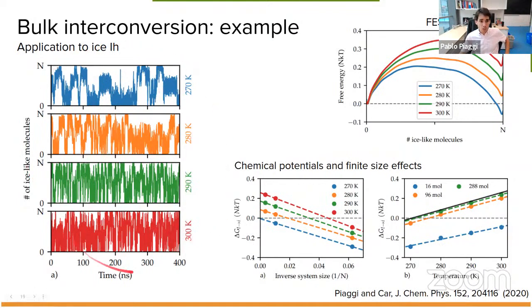So from these equations, one can compute the free energy surface that is not required directly to get the chemical potentials, but it's, I think, nice to see. What you see here is that we're actually simulating the nucleation process in which there is a very large barrier. We have here the liquid and here the solid phase.